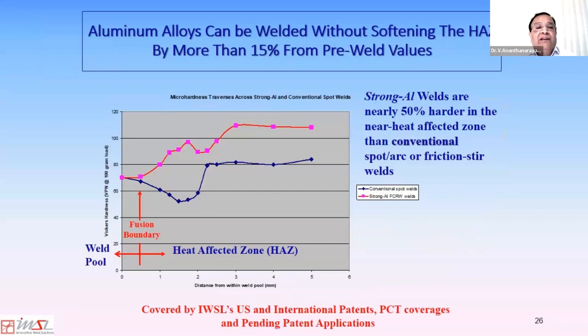And if you look at micro hardness profiles of these focused melt resistance welds and conventional welds, you can see here the darker bluish black profile is the micro hardness traverse across conventional resistance spot weld. Here is the fusion boundary.